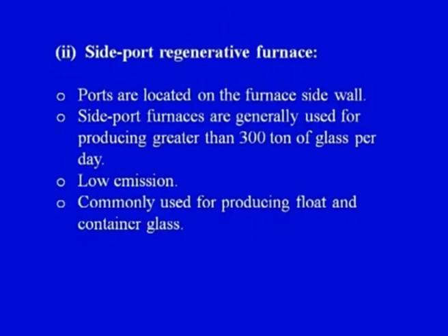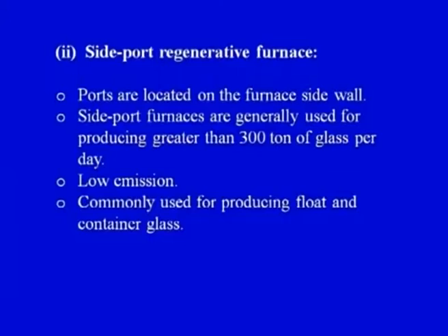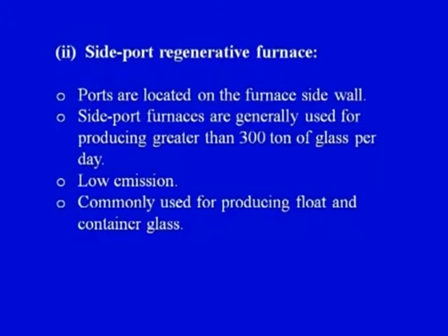On your screen you can see we have a side port regenerative furnace. In side port regenerative furnace, ports are located on the furnace side wall. In case of end port type, the ports were located at the back wall. Here the ports are located on the side wall. Side port furnaces are generally used for producing greater than 300 ton of glass per day. So we can see the production rate is also given. The emissions are low, so it is environment friendly and commonly used for producing float and container glass.